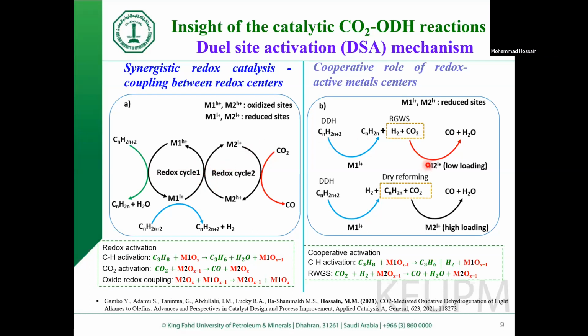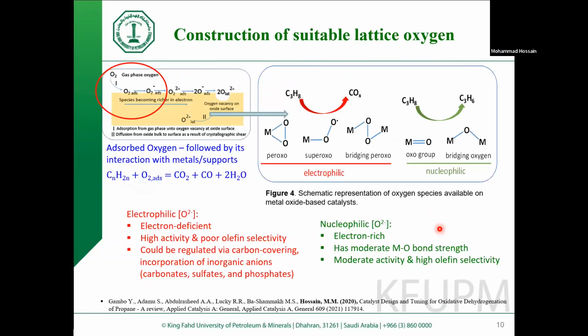There is another mechanism here, just like a cooperative role. In this case, hydrocarbon can be dehydrogenated by the reduced form of the metal to get olefin, and this way it will produce hydrogen, and hydrogen can interact with CO2 in a reverse water gas shift reaction. And then in another one, hydrocarbon can be dehydrogenated to form hydrogen and olefin. In this case, instead of hydrogen, olefin can react with CO2 to achieve CO and hydrogen. So this way, the cooperative role can be established, and one has to remember in this case, the loading of the second metal plays an important role in determining which reaction is going to be dominating.